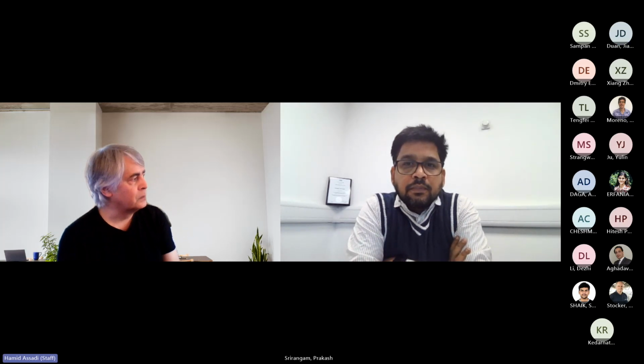Thank you. Yes, well, it's a very, very good point. I know that people have been looking at that specific question, and yes, it does play a role. But I think they focus on the level of oxidation on the particles rather than the substrates. For substrates, when we first wanted to introduce cold spray in different conferences, going around and saying why cold spray is good, I just mentioned two things. One was the fact that it is at solid state, so it reduces oxidation. The other one is that it inhibits phase transformation, etc. But that was another thing. So you don't really need surface preparation because it's kind of doing the job itself.